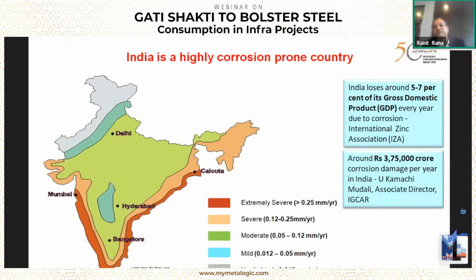And when we select a material, we also need to consider the environment that we are operating in. And as you can see from this diagram, this is called the corrosion map of India. And as we can see, the coastal regions experience extremely severe corrosion of more than 0.25 millimeters per year. And as we move inwards, the corrosion decreases, but even by any standards, this is much higher than what we experience in other countries.